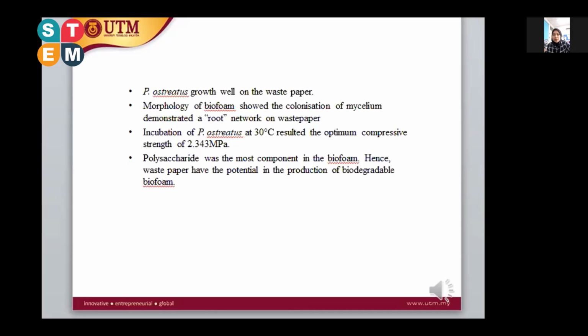Based on the compressive strength, the biofoam incubated at 30 degrees resulted in the optimum compressive strength, and the morphology of the mycelium showed that the colonization of the mycelium on the waste paper demonstrated a root network on waste paper, while the chemical characteristics of biofoam were tested and indicated mostly polysaccharide contained in the biofoam. So waste paper has potential in the fabrication of biodegradable biofoam when it is colonized with suitable fungus and incubated at the optimum environmental conditions.